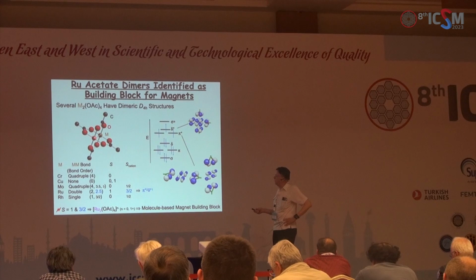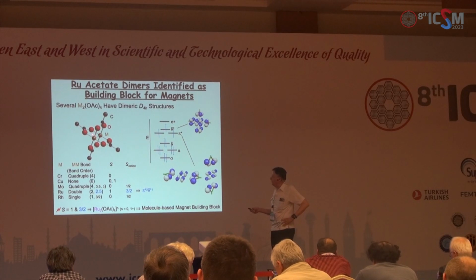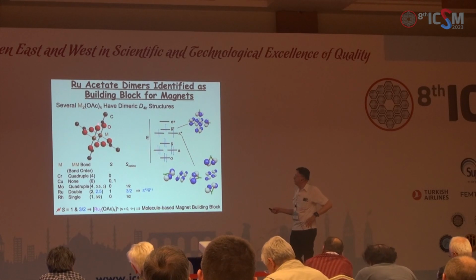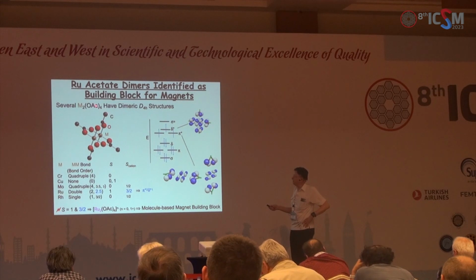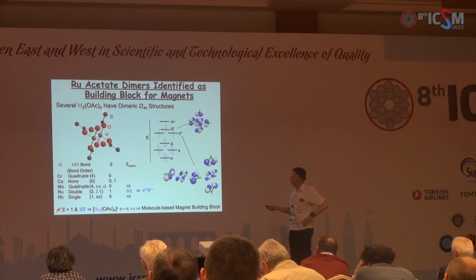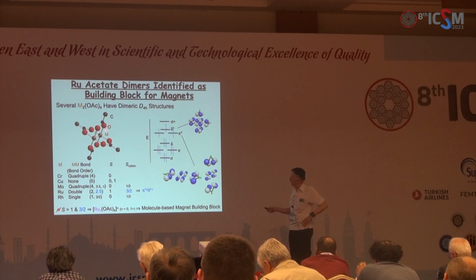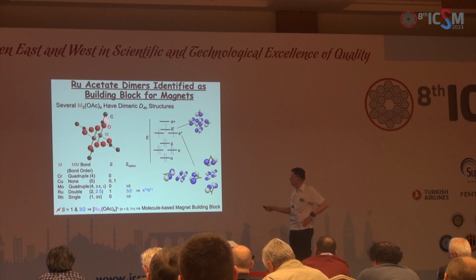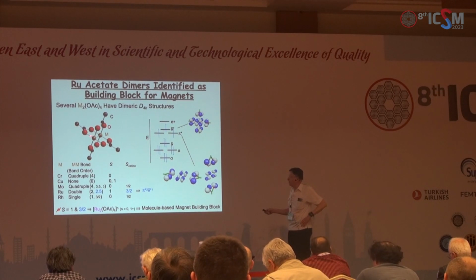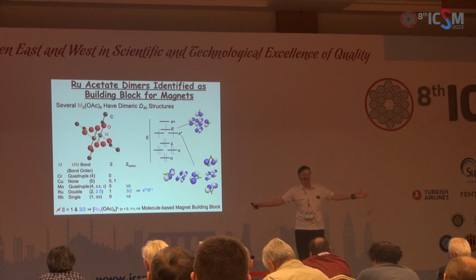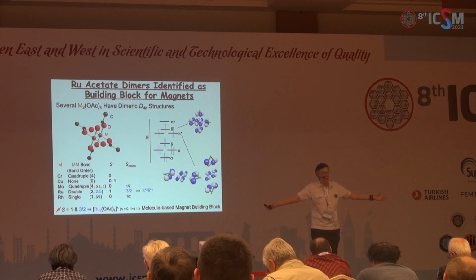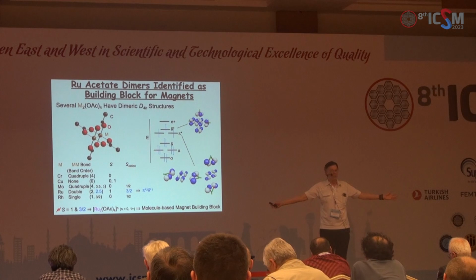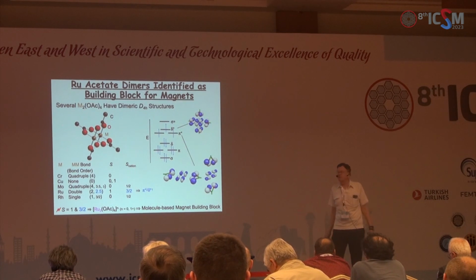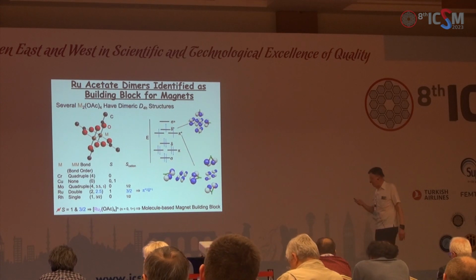These brown balls are a metal site surrounded by acetate: 2 oxygens, a carbon, and some organic group, in this case methyl, so it's an acetate. Each of these oxygens bridges both metals, giving a pinwheel of D4H symmetry for this material. If these metals are copper, you think about the Landé equation and spin coupling in copper(II), and there's no bond between the metals—a nice piece of physics, very important to the evolution of magnetism.